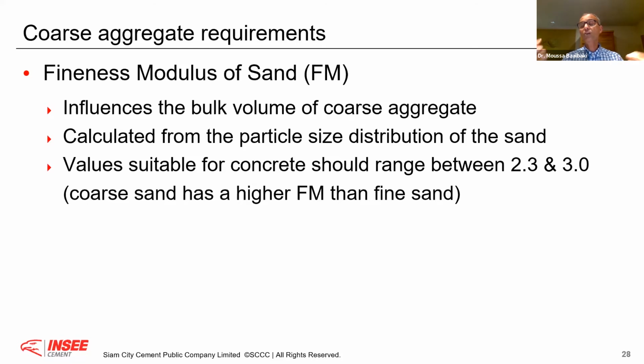Therefore, if you cannot increase the cohesiveness of your mix, suddenly you have a problem of bleeding. For example, if I switch from natural sand to crushed sand, like quarry dust, and if my modulus of fineness from natural sand, that is normally around 2.6, goes above 3, 3.1, 3.2 for quarry dust, suddenly I miss a certain cohesiveness, and I can have more bleeding.